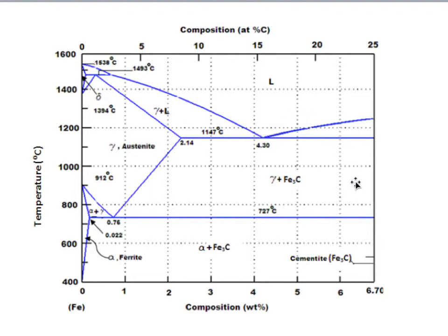An important feature here is also the cementite phase. It's a compound, Fe3C, which has 6.7% carbon, positioned here. And it's important as it is one part of this two-phase region, this two-phase region with ferrite and cementite. And therefore cementite is an important phase in the structures formed in this region, in the regular steel structures. So let's start now to focus on this part only and look at some transformations occurring here.